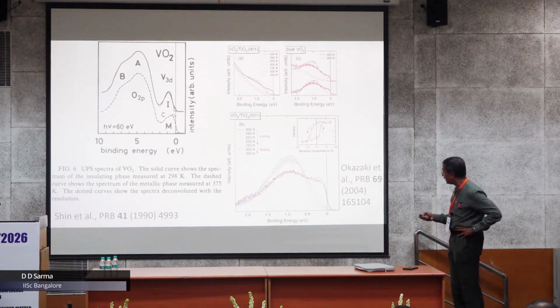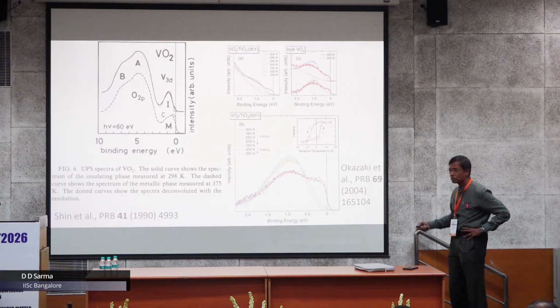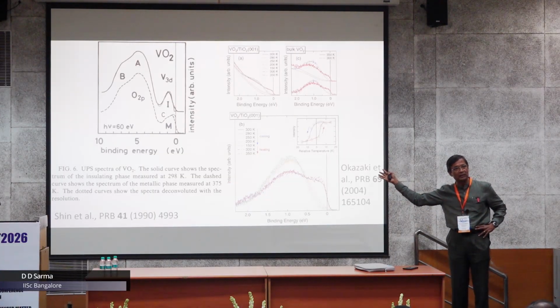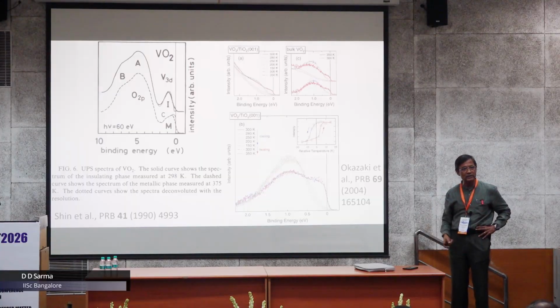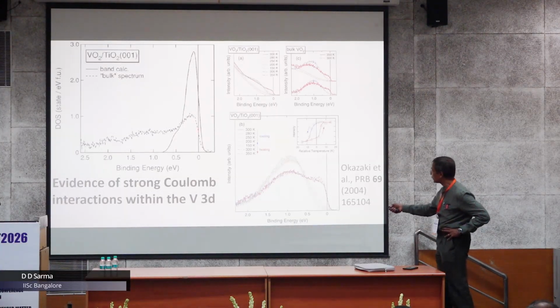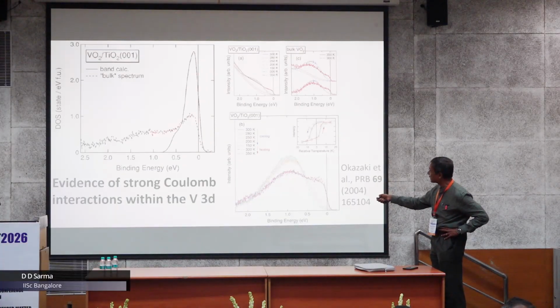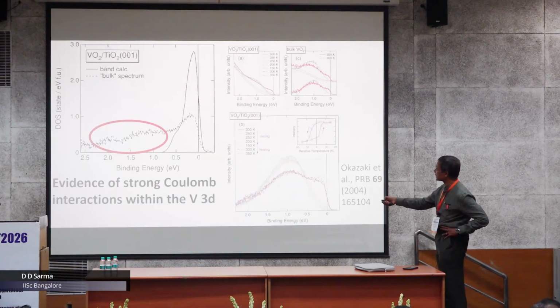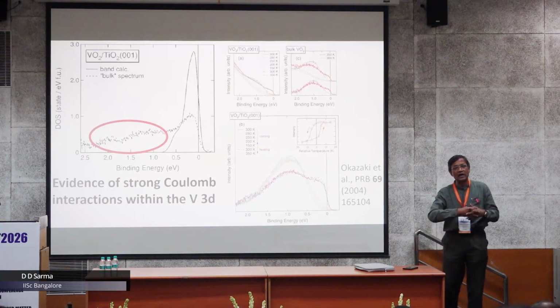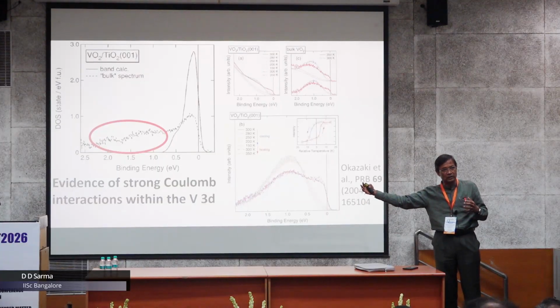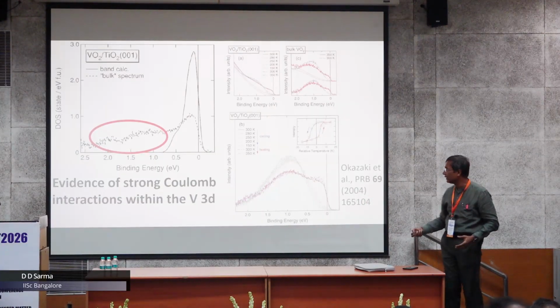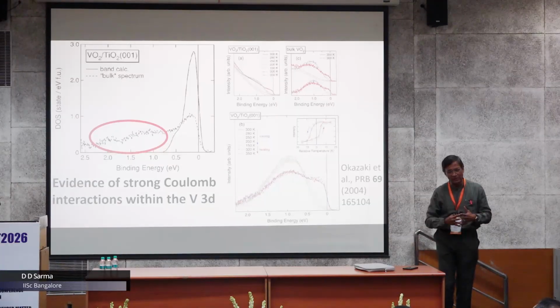And that's true because if you were to try and explain these states from the band structure calculation that PRL claimed in 1994 is enough to understand, you would find that it cannot understand at all, because density functional theory with no correlation effect will describe the spectral weight to look like this. This cutoff is essentially coming because of the Fermi-Dirac cutoff of the occupied part, but this large amount of intensity that is lying outside the DFT calculation predictions is coming because of correlation, which drives the spectral weight out of the single particle description and throws it over a much wider energy range, and that you can see. So correlation plays a very important role.